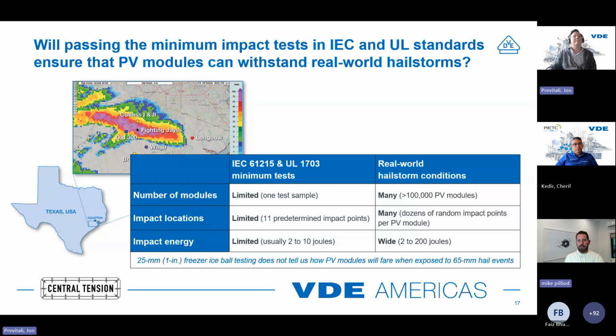And when you look at the standard tests that are out there from a pass fail perspective, in automotive we did things like crash testing, where you're doing a qualifying test for a module. These binary pass fail tests are not a bad thing as far as qualification, but what they don't tell you is if you pass it, how good did you get? How far away from failure were you? And if you failed, how close were you to the failure point? To do that, you need to do what's called the staircase method, or be able to start increasing energy to be able to look at failures as far as when something failed.